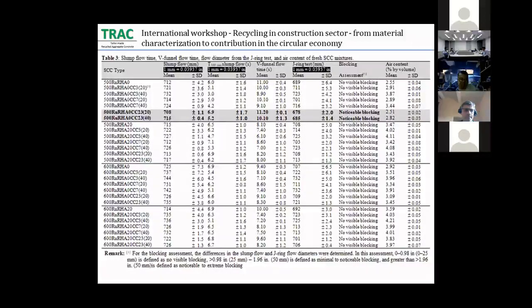When considering the time to reach 500 millimeters in diameter, using calcium carbonate can reduce the flow time, for example from 6 seconds to 3 seconds. This decrease can be explained by the finer calcium carbonate having a higher air content, which improves the flow characteristics of the self-compacting concrete. The greater dispersion of calcium carbonate decreases the viscosity, which means the resistance of the self-compacting concrete to flow under an applied shear force, resulting in higher fluidity than the controlled self-compacting concrete.